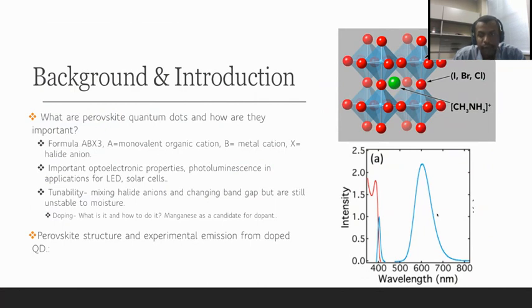And so one way to stabilize them is to change the atomic radius, because I've read that atomic radius can also affect how stable they are. And also to use dopants. One good example of a dopant that can be used is manganese. Manganese is able to make it stable, and also change the PL to around 600 nanometers, as the figure at the bottom right shows. Next slide, please.